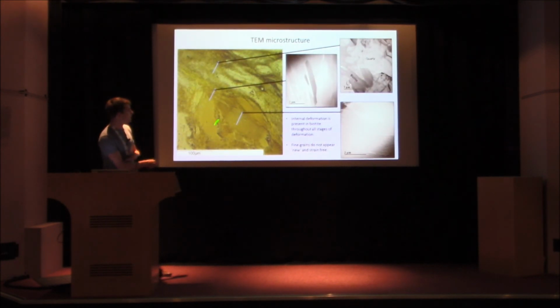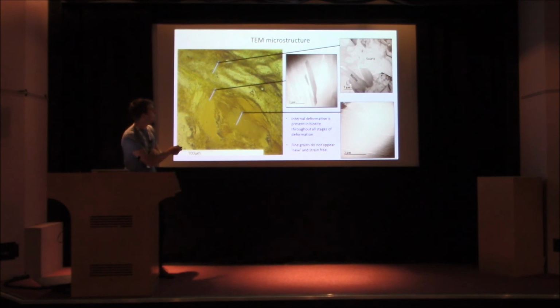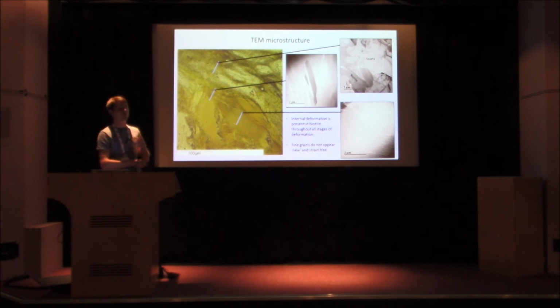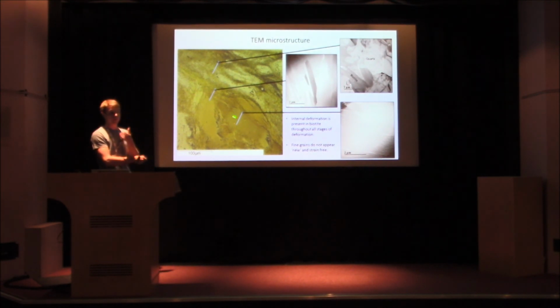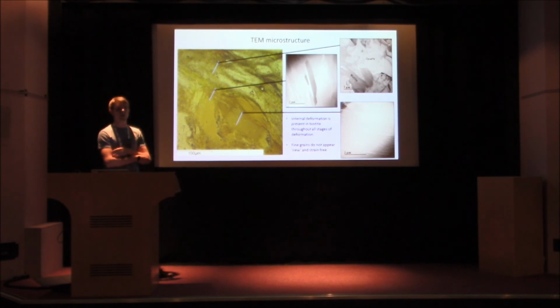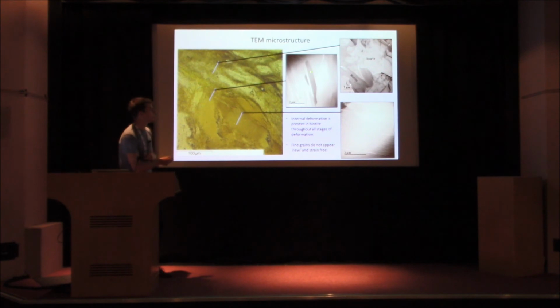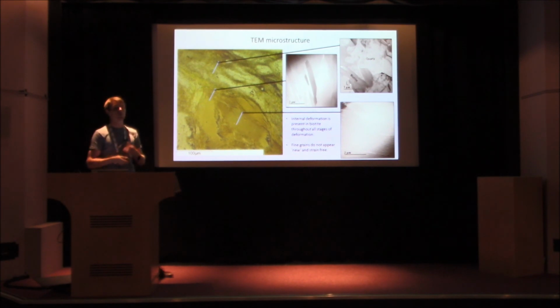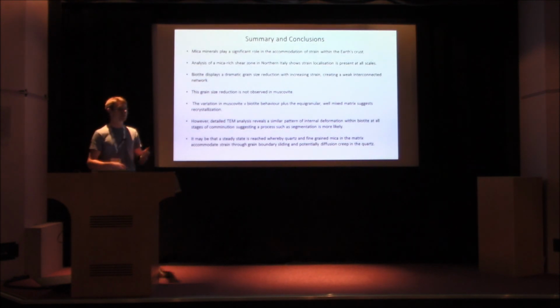And what you can see here is a grain that's coarse, and then some of the breakdown product, and we caught it in the process of breaking down, as it were. This internal deformation, this internal damage, is present in all three stages of this deformation. So in the old grain, which you'd expect to be damaged internally because it's been kinking and bending, but also in the newer, smaller grains that we thought maybe were dehydrated and recrystallized, maybe fresh grains. Well, actually, we see this kind of internal structure that hasn't been seen very much before is present in all stages. So that would suggest potentially we're looking more at the segmentation mechanism, whereby these are smaller pieces of the old grain. So the next stage is to work out exactly how that segmentation process occurs.